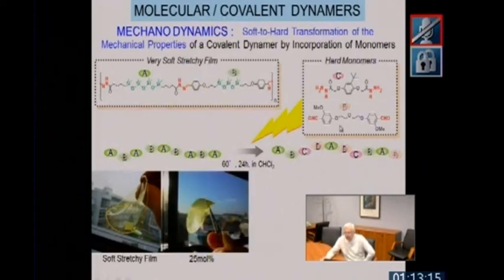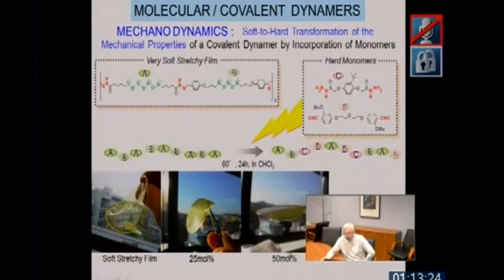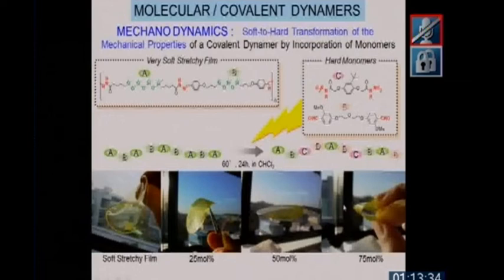With 25% of these hard monomers, you see that the film now looks already much better. Not so soft, not so stretchy anymore. With 50%, it is now mechanically strong enough not to bend anymore over its weight. With 75%, the flexibility is still there, but it is a more resistant, stronger film.